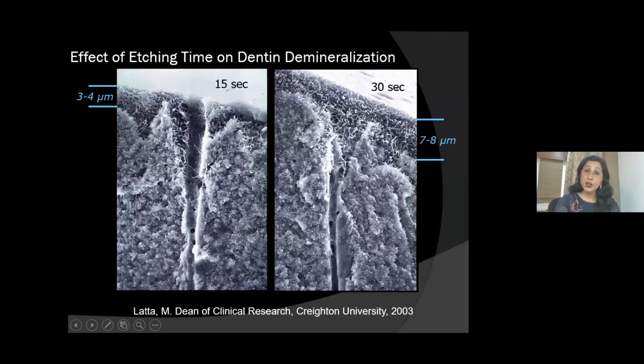But when you etch for 30 seconds, the dentine is demineralized for 7 to 8 micrometers, and the bonding agent fills only the 3 to 4 micrometers, which means that the remaining unsealed dentinal tubules permit dentinal fluid flow during thermal and tactile stress, which in turn stimulates nerve fibers in the pulpal tissue. This is the primary cause of post-operative sensitivity, and the patient experiences it when eating or drinking hot or cold food, or when simply biting on restored teeth. So always remember to etch only for 15 seconds, both for enamel as well as dentine.